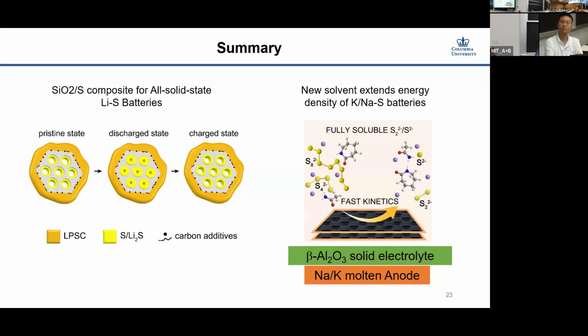Okay, to summarize, I showed 3 examples of using solid electrolytes to solve problems in alkaline metal sulfur batteries. In the first part, using the insulating solid electrolyte, we have surprisingly good effects for improving the performance of all solid state lithium sulfur batteries. This provides a rethink of the design matrix for the sulfur cathode. On the other side, we define a new solvent to expand the energy density in potassium sulfur batteries by dissolving all sulfide and polysulfide inside.